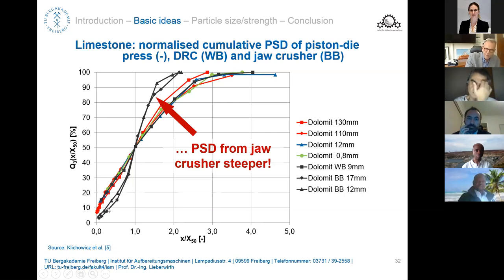And the explanation is very simple. If you look at the operation of a double roll crusher, in particular the flat face, but this is the same for all double roll crushers, your comminution appears in one pass. The material is drawn in, then it is comminuted, and then it falls out. In the jaw crusher, the material is comminuted in steps. You may also end up with a reduction ratio of 5 or 6, but then you release the material. It has time to reposition itself, and you might even have a classifying effect with some fine materials passing the crushing chamber earlier. That is why with a jaw crusher you typically see a steeper particle size distribution curve than with a double roll crusher, as you can see here.